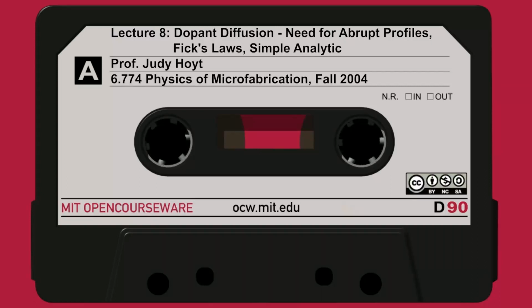The problem with it, of course, is that the implant process occurs at high energies. It actually damages the crystal to a certain extent, and we have to heal this by an annealing process. But unfortunately, the damage itself can enhance the diffusion rate, and we're going to spend some time in this course talking about transient enhanced diffusion. The dislocations or extended defects associated with the damage can lead to junction leakage, which is not desirable. And you may have some channeling of the implant. We'll talk about how that affects the profiles in Chapter 8.